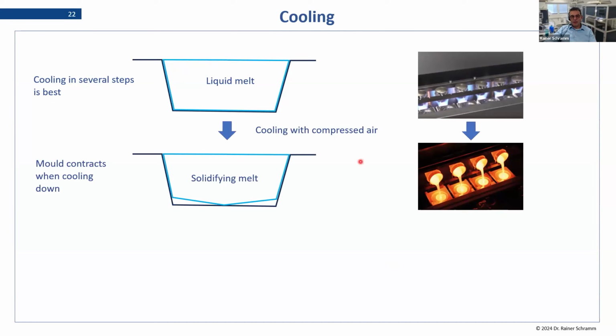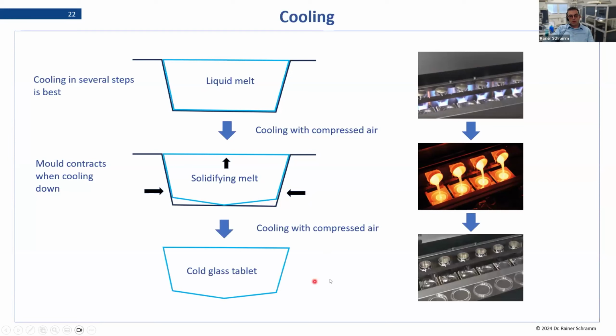And this has a reason, because if you cool with air, immediately there is an air bubble formed underneath your melt and the mold, and this will help to release your bead afterwards, because while cooling down, the metal of your mold is of course shrinking, and this helps then even to release your bead. And so that's why air cooling is an excellent tool. If you use a fan or you use just nothing to let it cool down, then it will be completely flat. And this means it will stick, of course, much more to the mold, and you need more release agents to get it out. So this is just that you know.